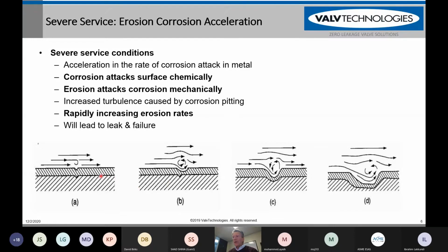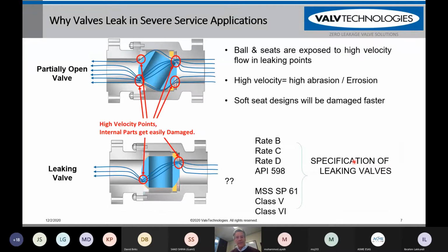Basically what it is that if you have a material and you have a corrosive environment, the internals of the valve will start to rust and to corrode. Then if coupled with that, you have abrasive service. The abrasive service continues to erode away the rust that is inside the valves and makes the corrosion be exposed to new metal all of the time. Over a period of time, this can greatly impact the valve, where you have corrosion and erosion happening at the same time, and can make for severe pitting in the valve.